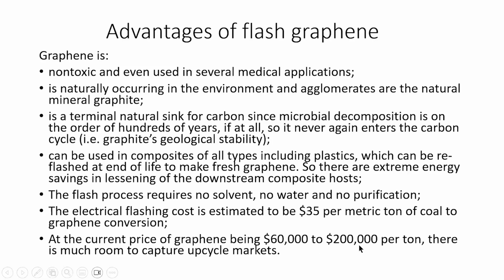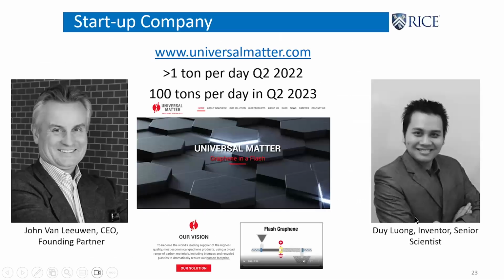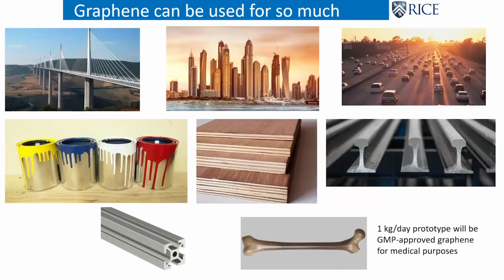It used to be 60 to 200 K per ton. Now it's 60 to 100 K per ton. It's come down. But here's the $35 per metric ton of coal to do this conversion. So there's Duy Luong, the senior scientist in the company, and here's John Van Leeuwen, the CEO. This 1 ton per day, they've hit this target. They have not hit the 100 tons per day, so this should actually be changed. They're just hitting the 1 ton per day. And then this automated system needs to be scaled up and multiplied.